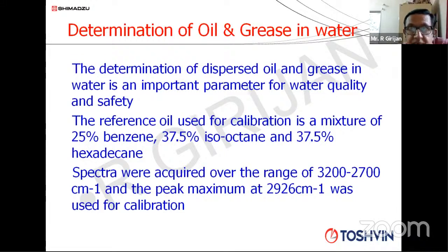And we should have a reference material for this quantification. And what's the reference material we are going to make? It's a mixture of 25% benzene, 37.5% isooctane, and 37.5% hexadecane. That's a standard material. Then we are going to measure the absorbance between 3,200 and 2,700 inverse centimeter, and the peak absorbance at the peak maximum at 2,926 inverse centimeter is going to be measured.